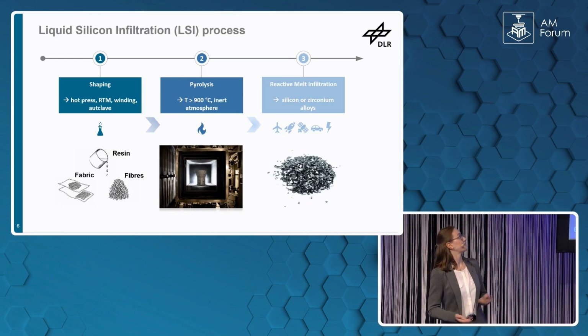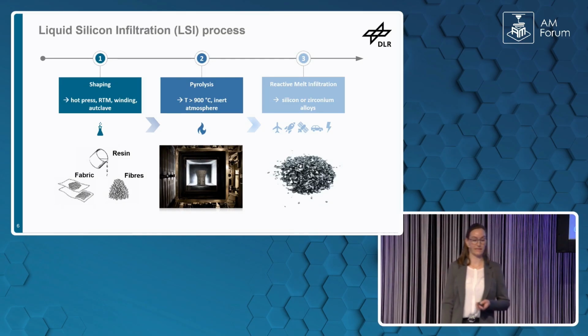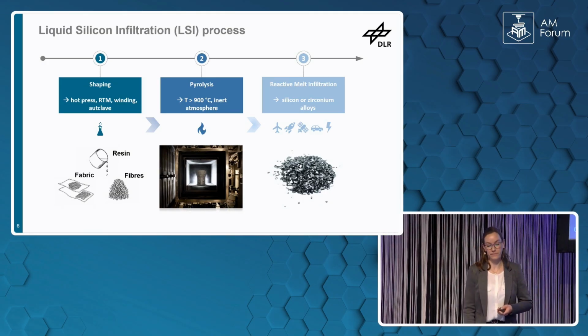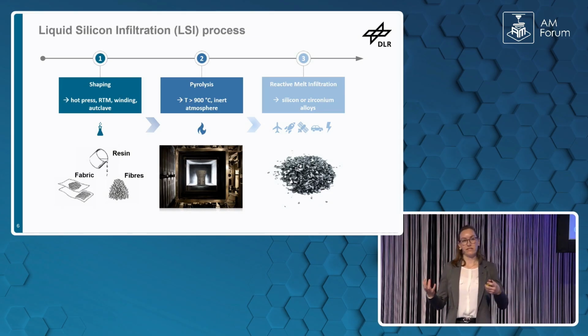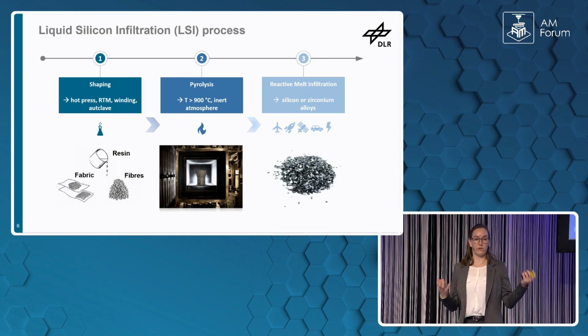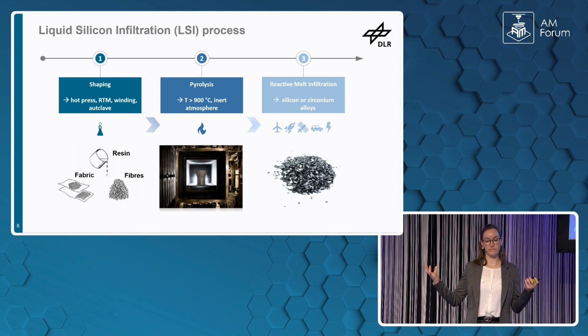The before-mentioned liquid silicon infiltration process, LSI, starts with the shaping of the green body. Fibers are integrated into a polymeric matrix. Then, pyrolysis leads to the conversion of the polymeric matrix into a porous carbon matrix. Finally, in the reactive melt infiltration step, a liquid melt from silicon or zirconium alloys, for example, is infiltrated into the porous component. And then, for example, silicon can react with the carbon, forming the silicon carbide matrix.